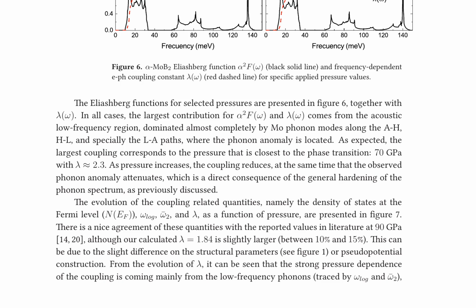The coupling strength, as represented by lambda, is highest near the phase transition at 70 gigapascals and decreases with increasing pressure. Figure 7 shows the evolution of these quantities with pressure, agreeing with reported values at 90 gigapascals with a slight difference attributed to structural parameters or pseudopotential construction. The strong pressure dependence of the coupling is mainly due to low-frequency phonons.